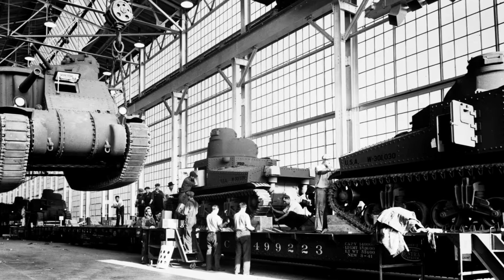The implications for the LST program were catastrophic. Every LST built used all welded construction. Every LST would eventually operate in cold water, either crossing the North Atlantic to Britain or operating in the Northern Pacific, or even just transiting during winter months. If LSTs were vulnerable to the same brittle fracture that killed the Schenectady, the entire invasion strategy was at risk.